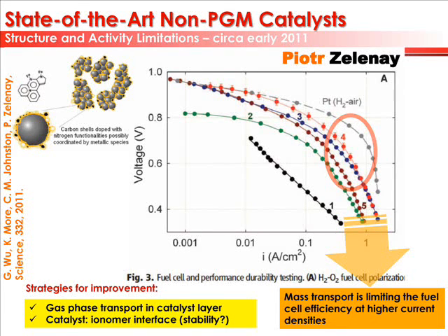Usually the end of the polarization curve, when it wears down, is when the transport dominates. The transport actually is present, and the ohmic losses are actually present throughout the voltammogram. So everybody who publishes high-profile papers fails to actually deliver exactly because of lack of transport. So they create catalysts that are good, but these catalysts don't work when the industrial vendor asks them to work.